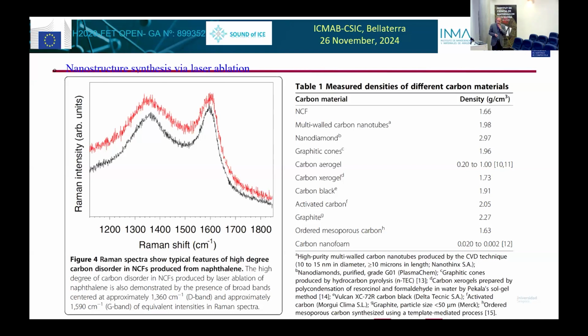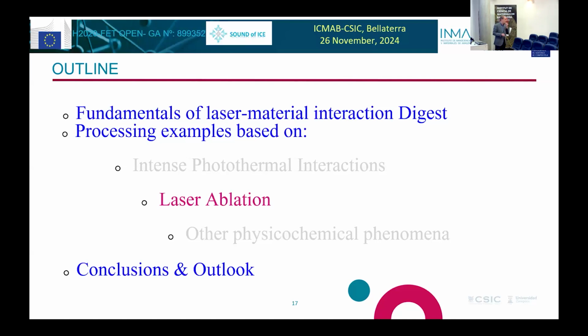And the amorphous structure, we found out that it originally came from the fact that we had phosphorus. For example, we use triphenylphosphine as a ligand. The presence of phosphorus generates what is called an intumescence effect. That means the phosphorus gathers all the hydrogen and forms phosphoric acid, and it prevents the molecule from undergoing combustion. It just undergoes a pyrolysis, and the pyrolysis yields this type of nanostructures that you see. So the amorphous part of the structure deals with the presence of phosphorus and the chemical reaction in the decomposition of this. But I never published that. I recognize that. It still remains to be published after so many years. But it's a very interesting phenomenon.